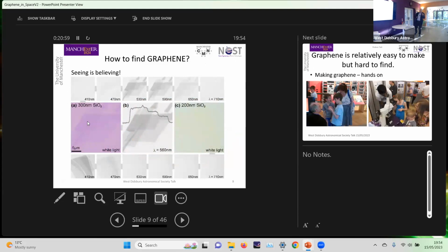Because if you look at different layers, for example, if you look at 410 nanometers up there, you can't see any graphene at all. And we discovered that when a new batch of wafers arrived with a different thickness of oxide, because we weren't bothered about how thick it was, as long as there was oxide there for some of our experiments, that's all we needed. And Kostya said, "Oh, I'm not making graphene anymore. Something's wrong." So he went away and he dug into various issues, what kind of tape he was using, etc., etc., and eventually what type of graphite, and eventually.